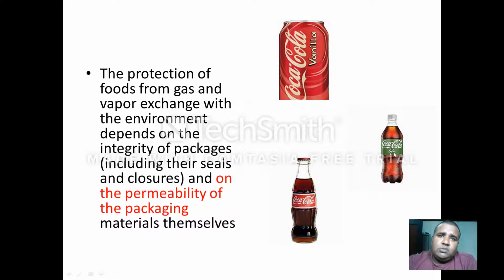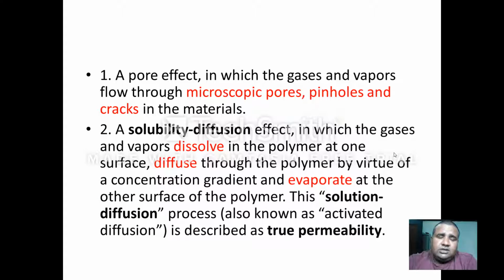In the third slide, I'll talk about what are the factors on which this permeability depends. Number one, there can be a pore effect, in which gases and vapor flow through microscopic pores, pinholes, and cracks in the materials. So if the packaging material is not intact and has some flaws, like microscopic pores, holes, or cracks, then via these minute openings the gases can be exchanged from outside to inside or inside to outside.